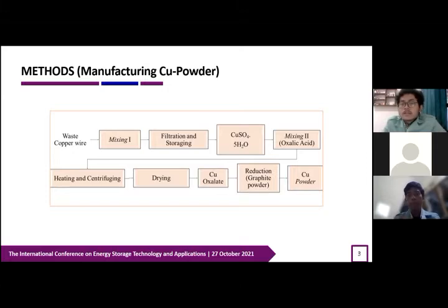copper sulfate pentahydrate. And in mix two, we added oxalic acid with the concentration 0.0125 molar. The precursor solution was made acidic by adding oxalic acid to form a salt. With the process of heating and centrifuging and then drying, it then forms copper oxalate. Then we reduce the copper oxalate with graphite powder.